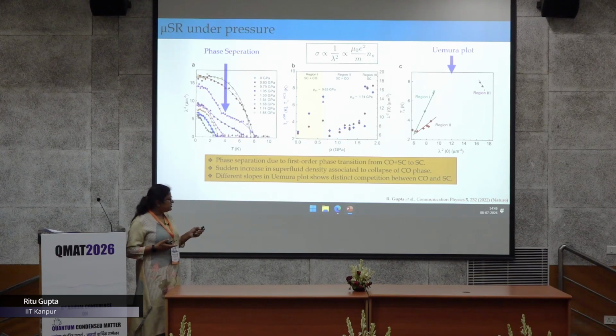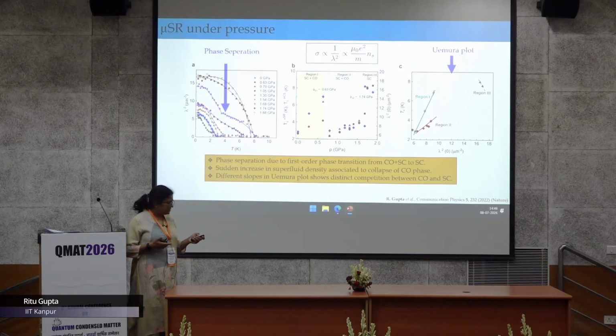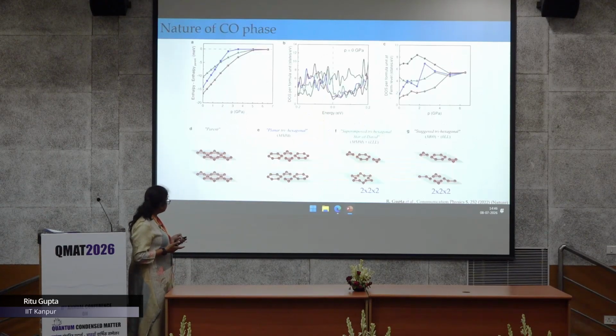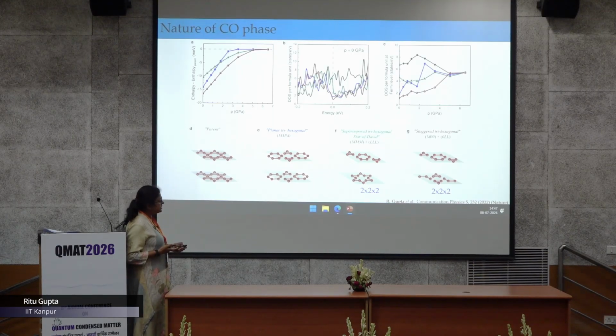We could not understand it with the experimental method, so we tried with DFT calculations. And there you see this parent one, which is the perfectly aligned Kagome lattice. And then these are the suggested models for the charge density wave: planar trihexagonal, which involves M point instability, Star of David, which involves both M and L point instability, and then staggered trihexagonal, which involves M and L both. And the periodicity for charge density wave order will be 2×2×2 for both of them.